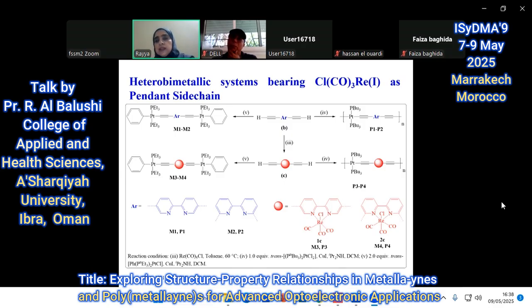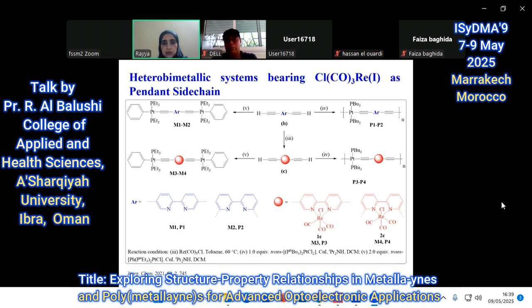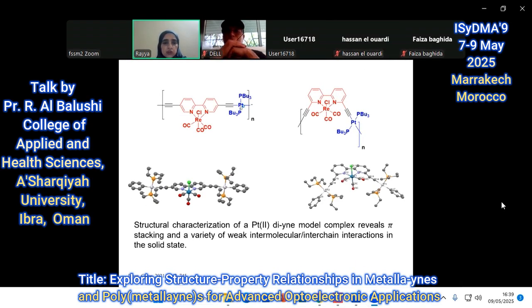Then we tried to improve the properties of our materials by incorporating a second metal. That means we have the spacer group. Now we just incorporated a metal as it is here. This is a spacer group. We already studied the bipyridine as a spacer group. Now, since we have this N there, there is a possibility for combination with rhenium. So we selected one rhenium unit in our material. We prepared the ligands first, incorporated the rhenium unit, and then added the platinum to have a system like this. So here we have two metals.